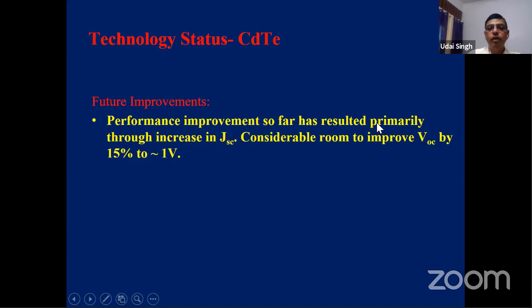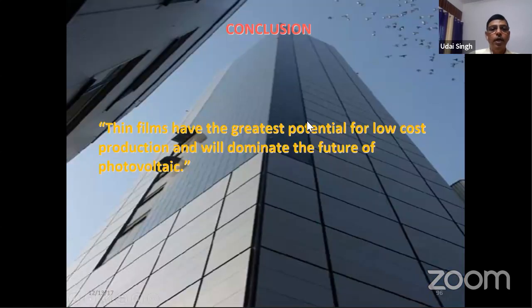The performance improvement so far has come from an increase in the short circuit current. There is still room to improve the open circuit voltage by 15%, because if you see, the band gap is around 1.5 electron volts, so the maximum open circuit voltage one can achieve is around 1 volt, but still 750 or 850 millivolts is what is obtained. Okay, so this is the last slide.